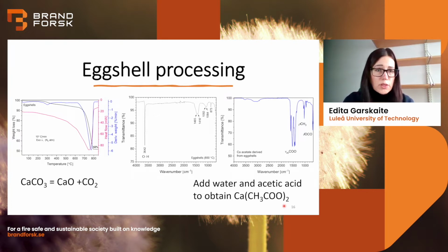And when we're processing eggshells, like I mentioned, we have calcium carbonate, which is the main phase of eggshells. And then when you anneal at higher temperatures, you need to perform thermogravimetric analysis in order to estimate at which temperatures you need to heat this material to get calcium oxide, pure calcium oxide, from which you continue further to make a calcium acetate and then use for wood impregnation.